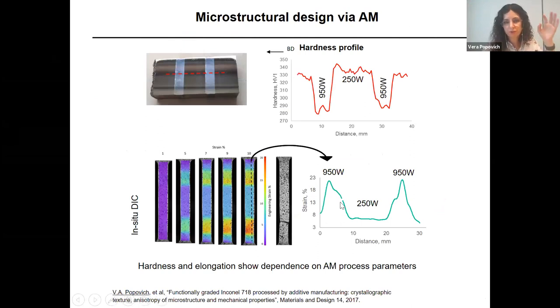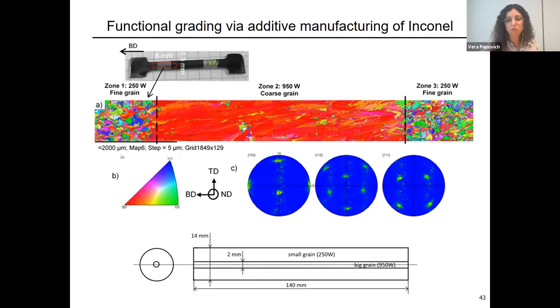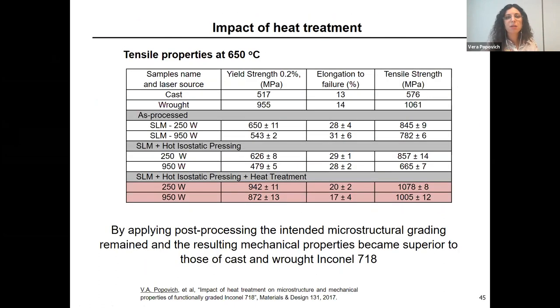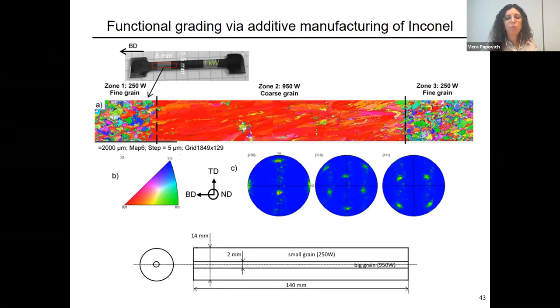So you have different strain, different hardness, different strengths, because the grain size controls this all as well, and the grain orientation. But more importantly, our concept with this was to tackle both fatigue and creep properties in, for example, turbine blades. Because for fatigue, especially at the initiation, you normally want finer grains, so to have more grain boundaries that impede the initiation of your crack, so kind of obstacles.